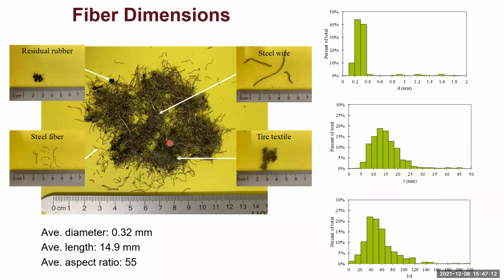Here is a picture showing the fibers from the scrap tire. As you can see, it is actually a mixture of everything, including residual rubber, steel wire, those big pieces still inside of the samples. We also have a lot of steel fibers, as you can see, those same particles, and we also have lots of tire textile in the mixture.